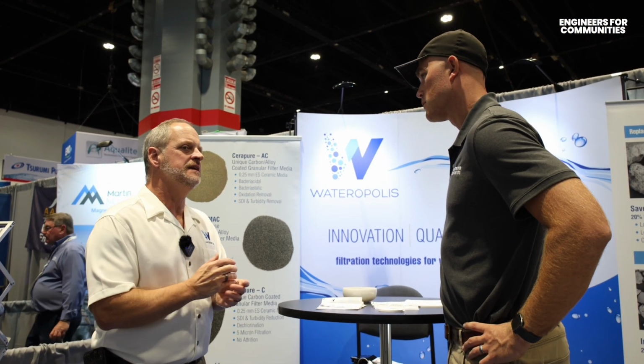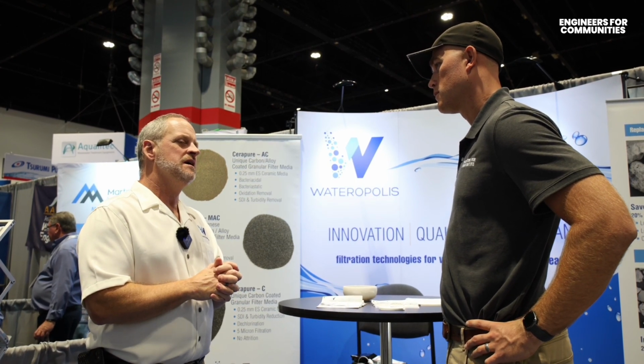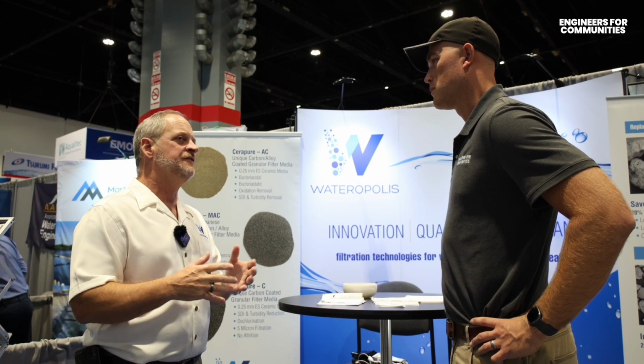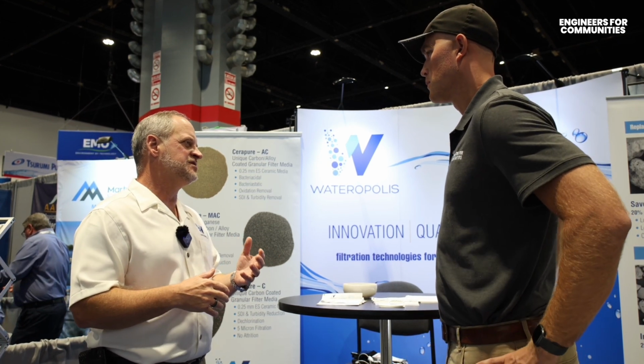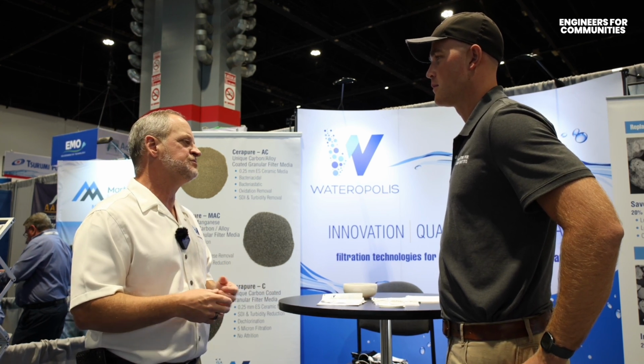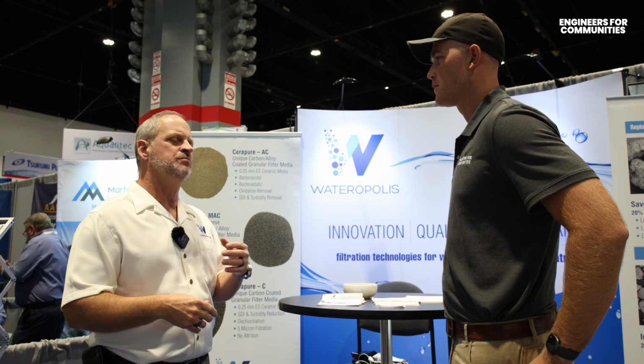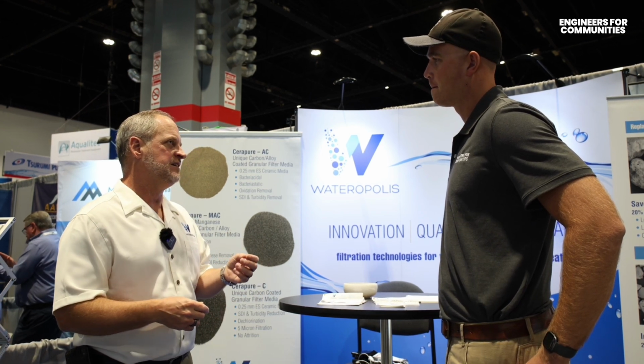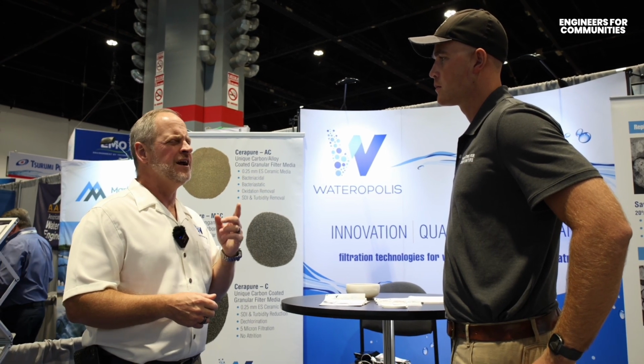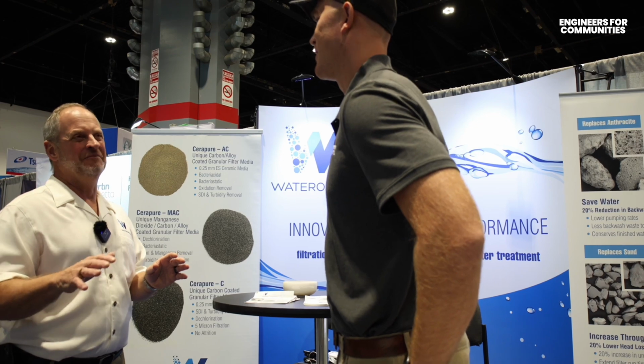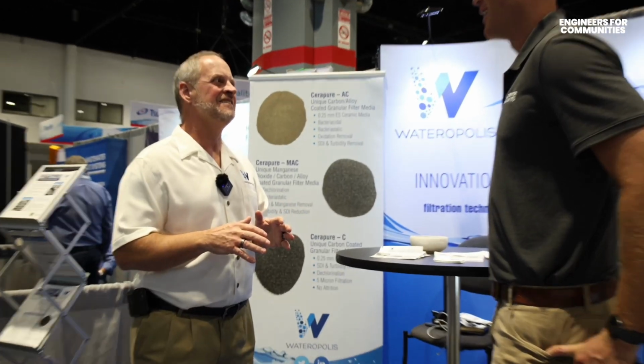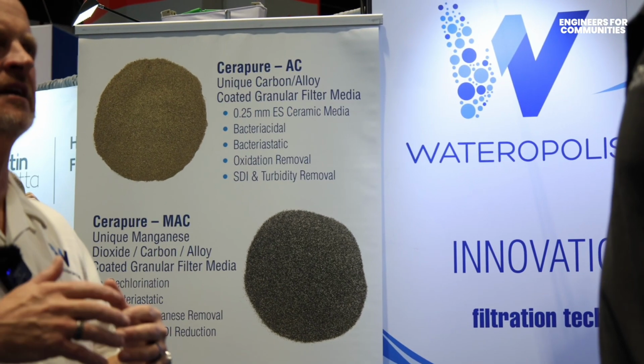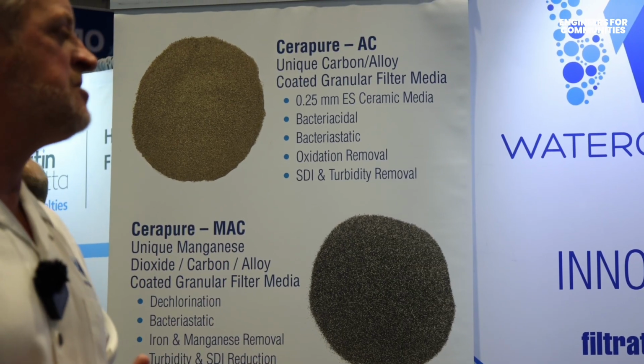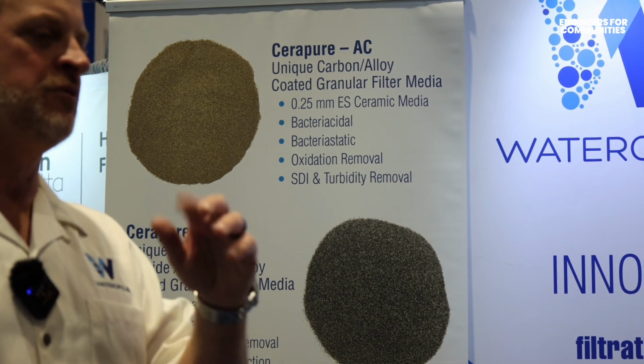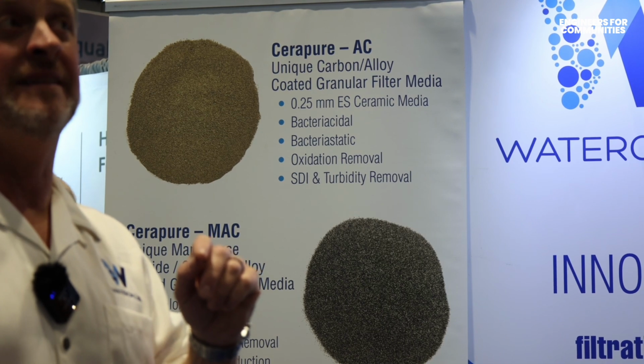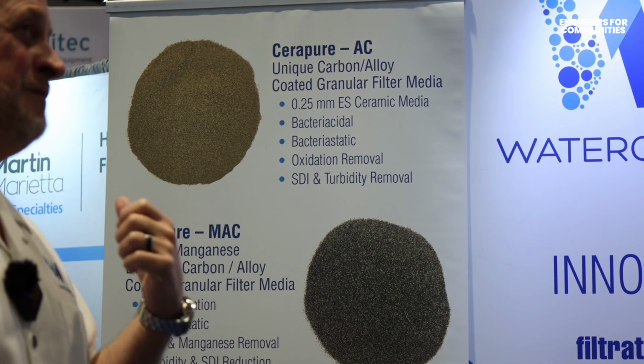So a lot of it comes down to what sort of oxidant you want to use. Most common in municipal drinking water is chlorine. If you're only using chlorine as an oxidant, you're kind of limited as to what kind of materials you can put in, whether it's for iron or manganese removal. We do get some clients that want to do peroxide or ozone. Then you have to think through, or air. Air is much less common. There was a day when I was young when air was used as a potential oxidant, but a lot of these minerals like iron and manganese don't have good kinetic response to air. They don't want to oxidize rapidly. So people moved away from air, but things like peroxide and ozone decompose to air, right? They turn back to air at some point, and they do it in the middle of your filter most often.